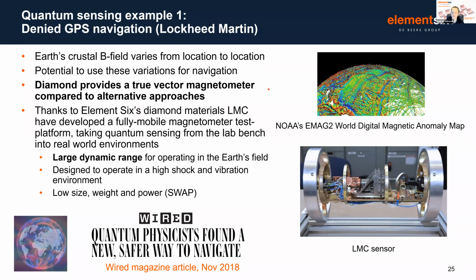And again, the critical thing here is that diamond NV based sensors deliver what is a true vector magnetometer solution compared to alternative approaches. It also has a very wide dynamic range, in addition to the advantages that we've heard about before in terms of being able to operate at room temperature. So you don't need bulky cryogenic equipment. So then ultimately, thanks to our diamond material that I've introduced, the high NV concentration material that we've developed, Lockheed Martin are able to develop a fully mobile magnetometer test platform, which has really taken this idea of quantum sensing in magnetic field sensing from the lab bench into the real world.